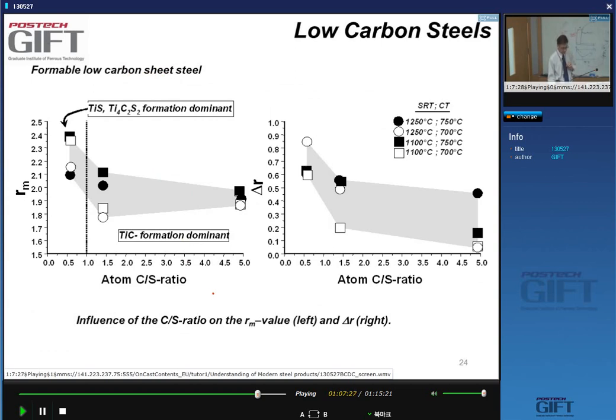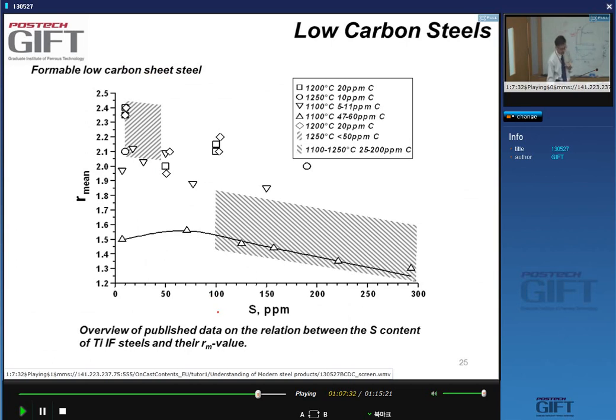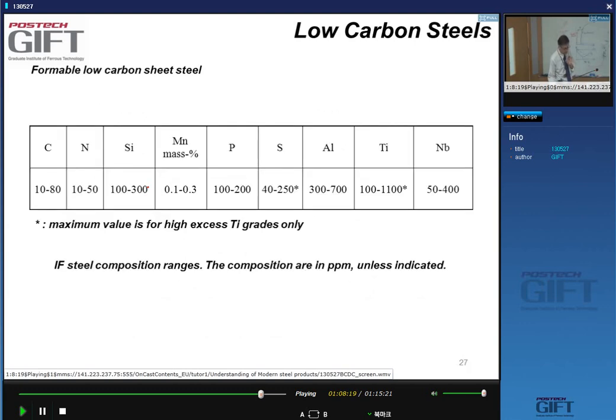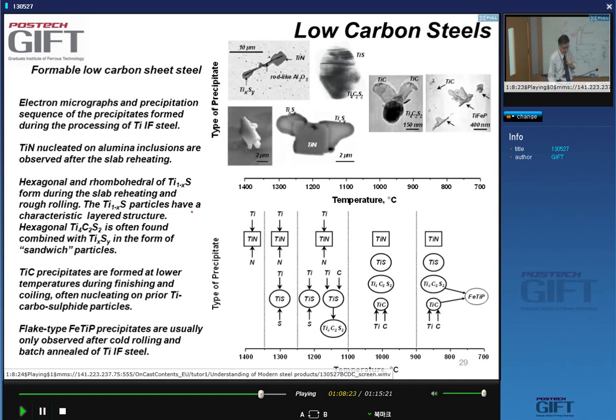And the reason is, it turns out that things are a bit more complex than I started explaining. The precipitation of carbon in IF steels can or cannot, it depends on the slab reheating temperature, become a function of the sulfur content. And why is that? The reason is very simple. Why is there an effect of the sulfur content?